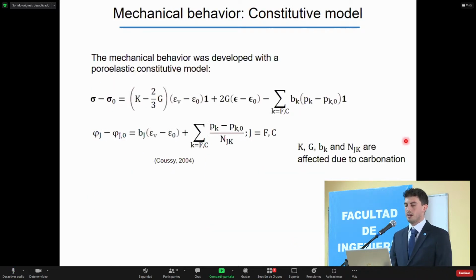The mechanical behavior was developed with a poroelastic constitutive model, which relates stresses with strains and the material stiffness, as well as the porosity and pore pressure. The values of K, G, B, and N are affected by carbonation over time.